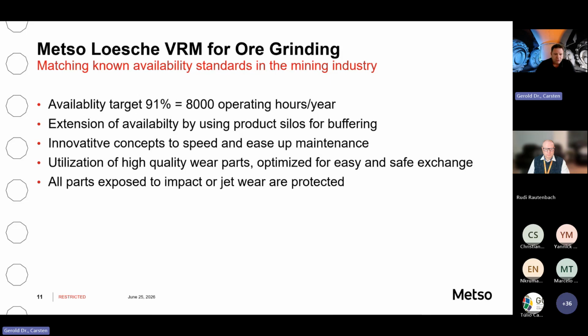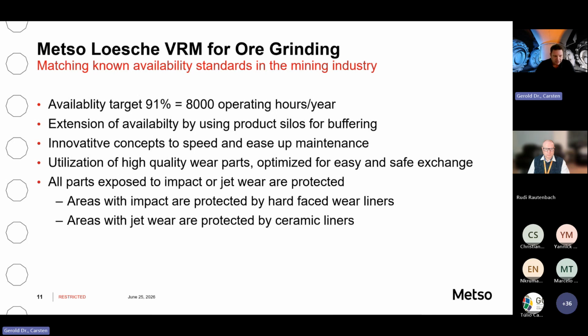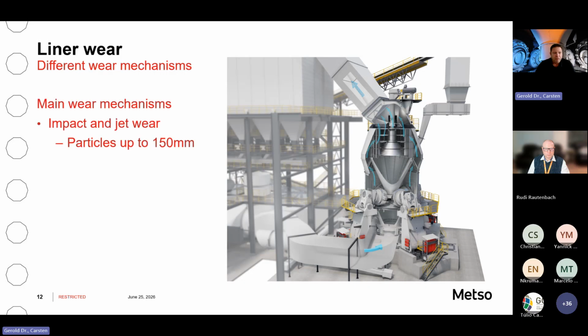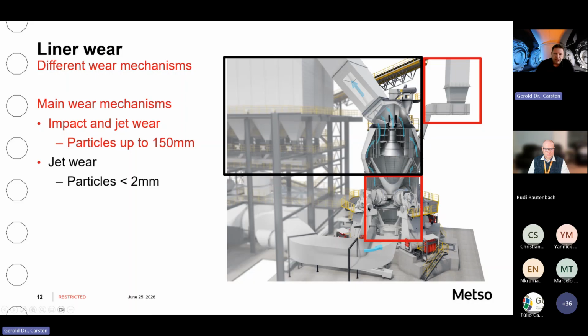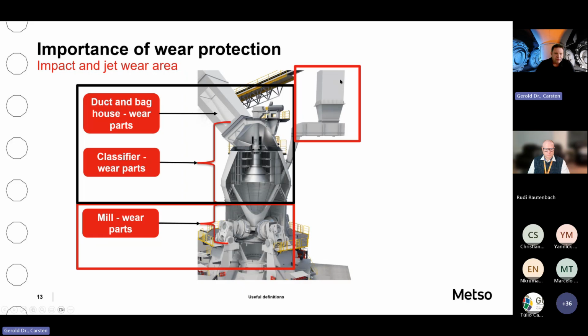In general, all parts that are exposed to impact or jet wear are protected. Everything that is facing impact is protected by hard-faced liners, and areas where we have jet wear are protected by ceramic liners. So taking a look at the different occasions of wear, the red circled areas are the ones where we have impact, which is in the feeding areas, but mainly when these particles up to 150 millimeters bounce on the table or are thrown around. So these are impact areas, while the jet wear is happening wherever you have the particle transport, inside the mill in the internal grinding classifying circuit, or when the particles are fine enough and they go to the baghouse. Therefore, we choose different wear products for the different areas of the circuit. And that makes it basically unique in the industry.